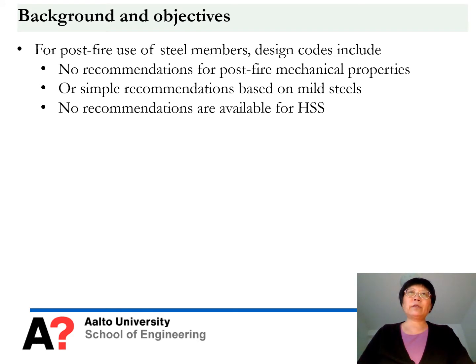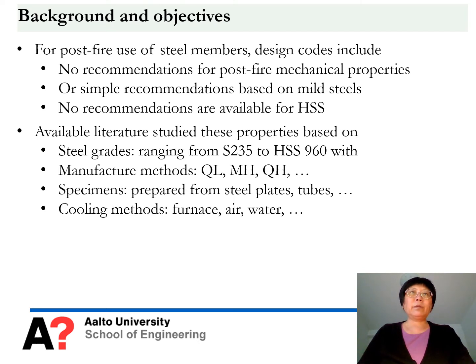For post-fire use of steel members, current design codes include no recommendation for post-fire mechanical property, or only simple recommendations based on mild steels, and no recommendation is available for high-strength steel. For that reason, available literature studies these properties on steel grades ranging from mild steel to high-strength steel using different manufacturing methods. The specimens were prepared from steel plate and tubular sections, and the cooling methods during the tests include furnace cooling, air cooling, and water cooling.